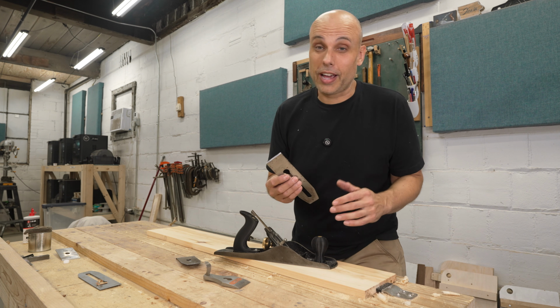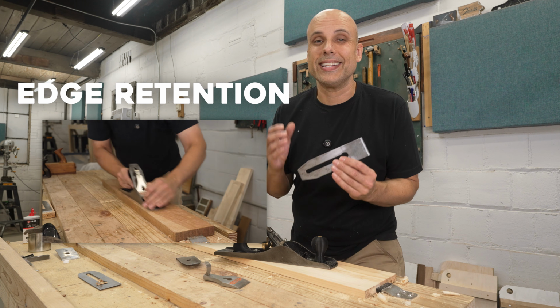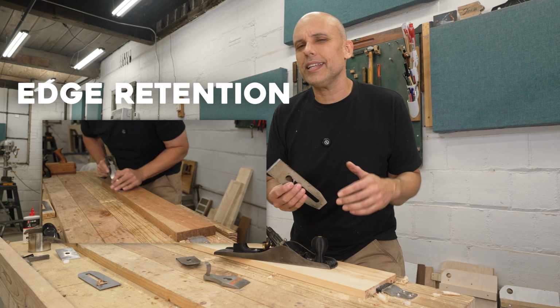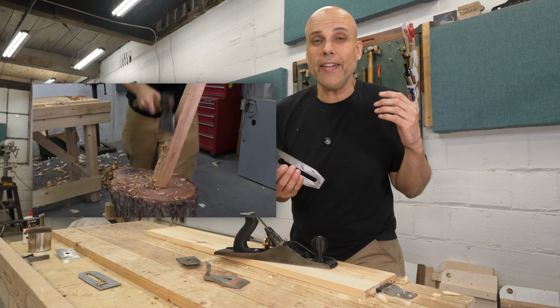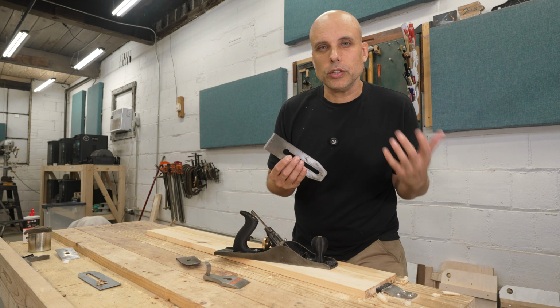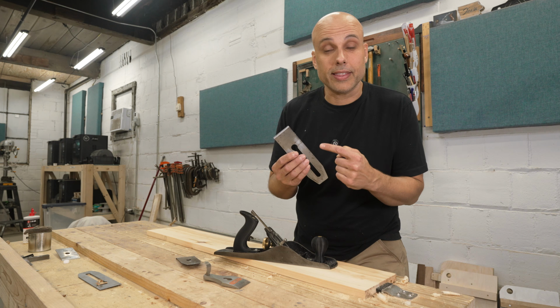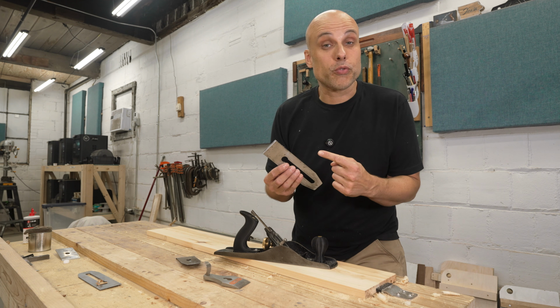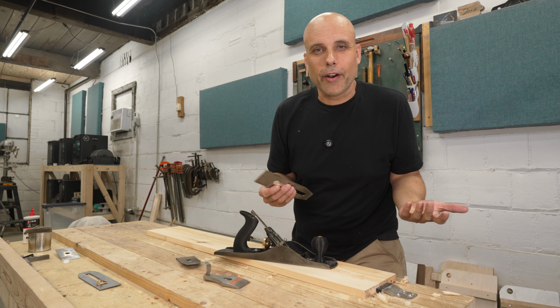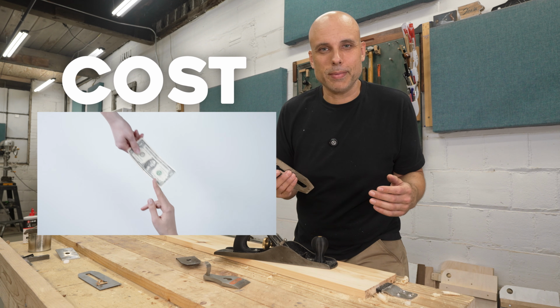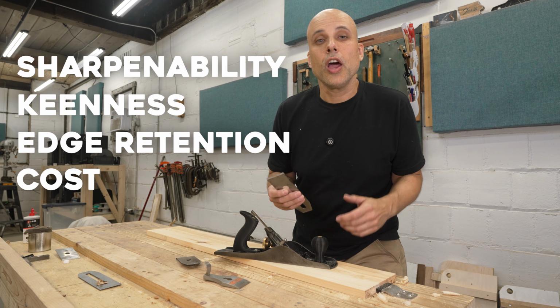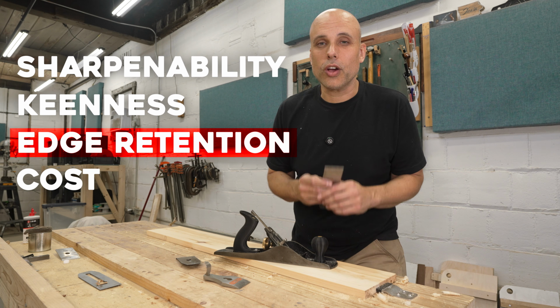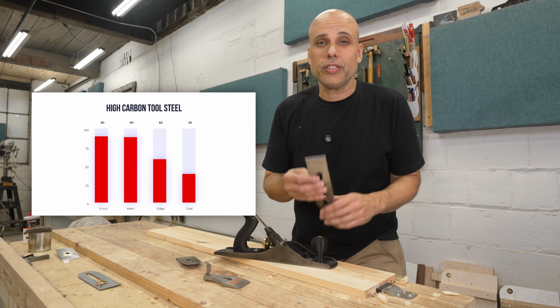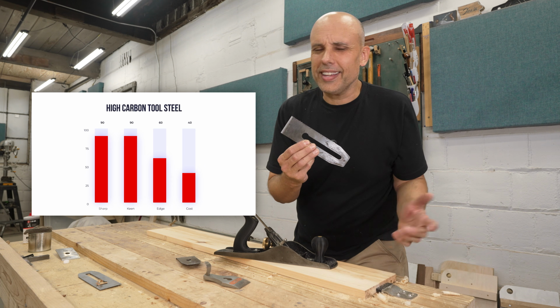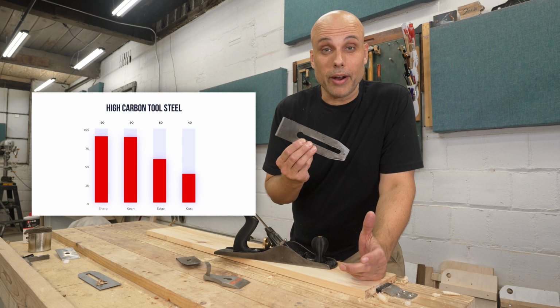A thing that people spend a lot of time talking about is edge retention. How long does a blade stay sharp when you're using it? And for this, high carbon steel is okay. It could be worse. For instance, axes and hatchets are made with a lower carbon steel, and they're made to be softer so they can stand up to impact, but they lose their edge more quickly. A high carbon steel blade like this doesn't have to get whacked against things, so the edge retention is pretty good. And of course, the last thing we care about is cost, because everybody's got limited money. So we could take these four things: sharpenability, keenness, edge retention, and cost, and we could put them in a chart. And if we look at the chart for high carbon tool steel, we can see there's nothing super amazing about it, but there's also nothing bad about it. It's pretty good.